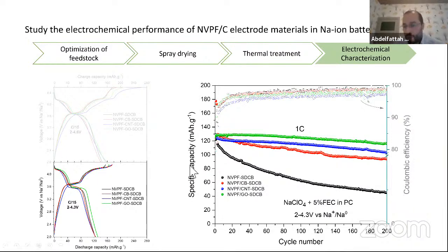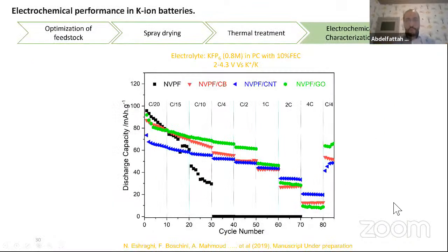Even though we are cycling our material for 200 cycles, we have very good cyclability and acceptable Coulombic efficiency. Compared to these three materials, those with carbon sources offer the highest capacity compared to the one without any carbon source, because we can see that its capacity decreases dramatically with cycling and reaches almost 1/3 of the initial capacity after 200 cycles. We also made some preliminary tests using this material as cathode material for potassium-ion batteries.